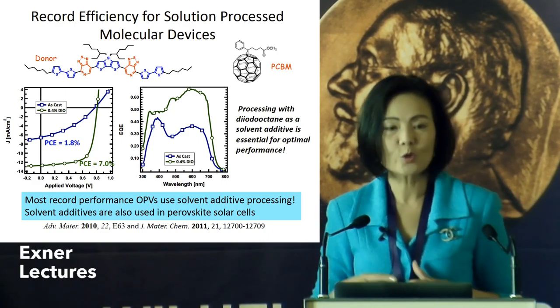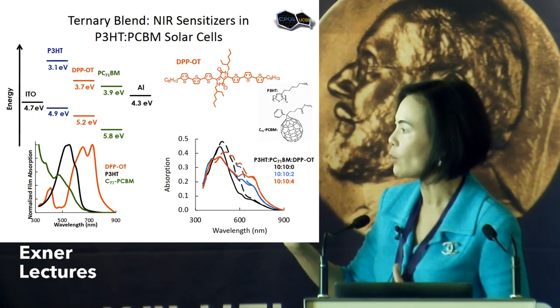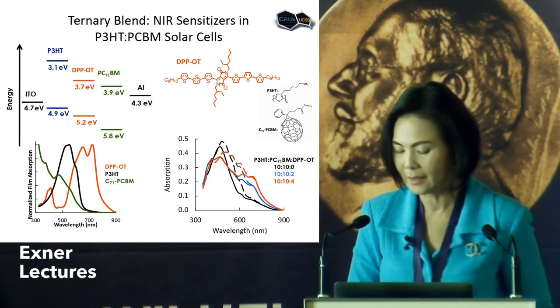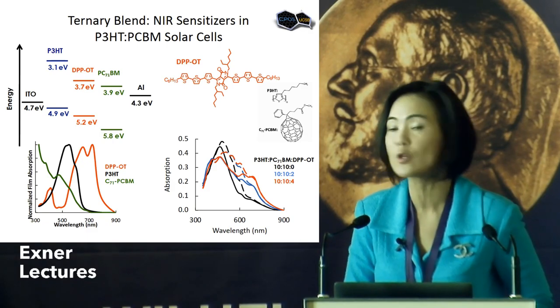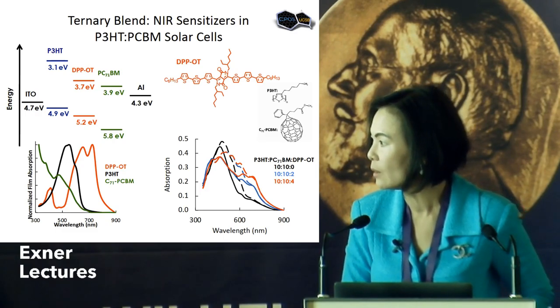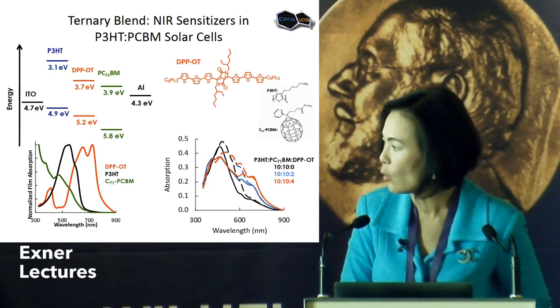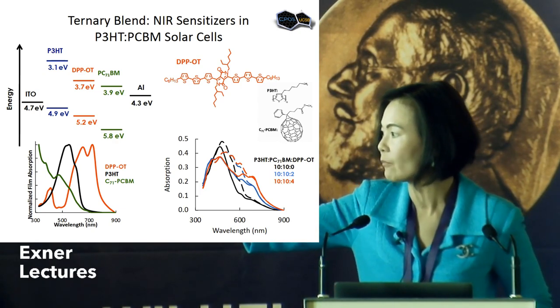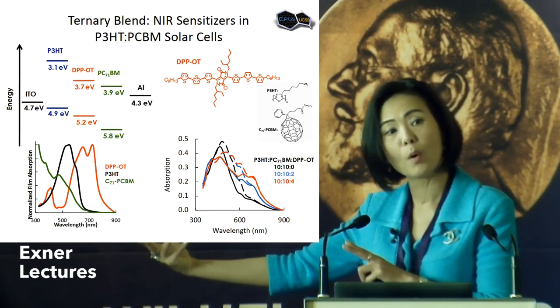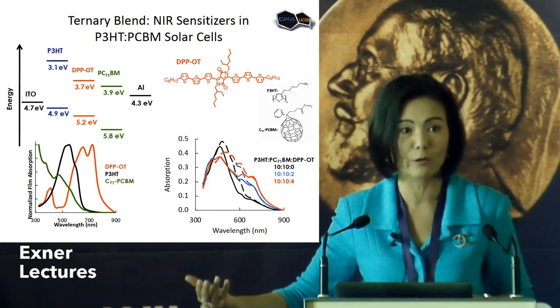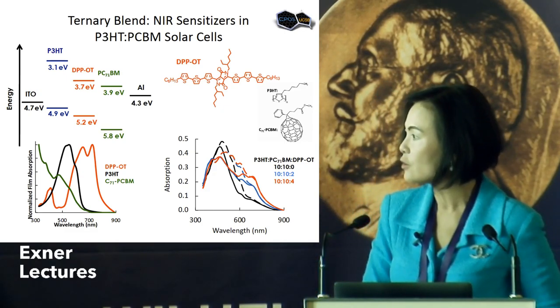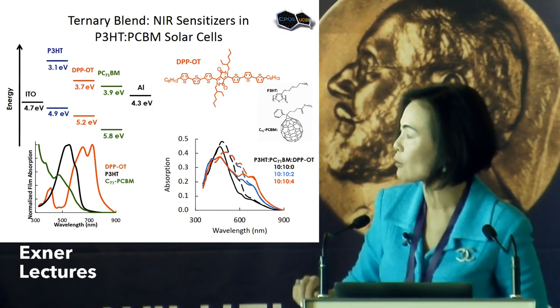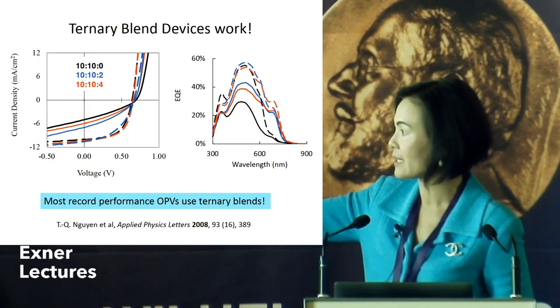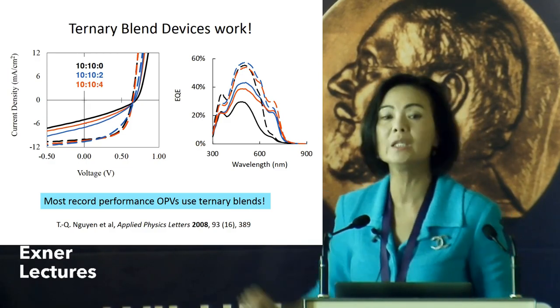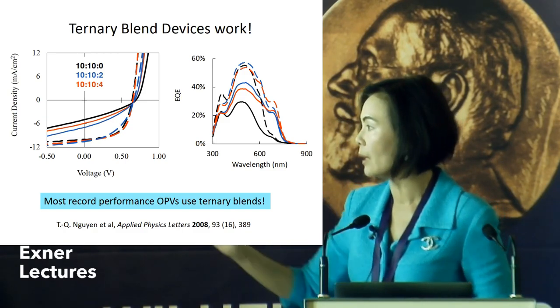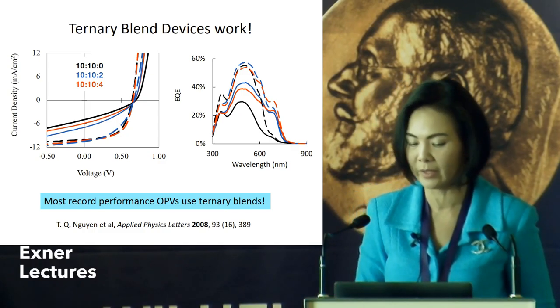And so besides that, very early on in my career, we also wanted to use ternary blends. Back then, we wanted to enhance the absorption of our active layer. And as you can see here, we have the donor and the acceptor, and the absorption ends at about 650 nanometer. So we had the idea that if we add another component that has absorption all the way close to 900 nanometer, you can enhance the absorption of the material. And that is basically what we did, and we reported it early on in 2008, the use of the ternary blend, and the right-hand side shows the external quantum efficiency. Indeed, you do see the photocurrent contribution extend beyond the donor-acceptor that we normally use, polythiophene and PCBM.